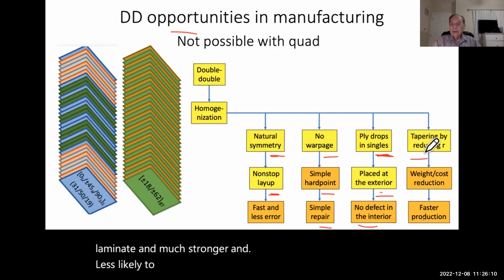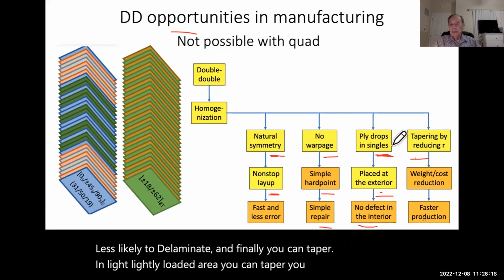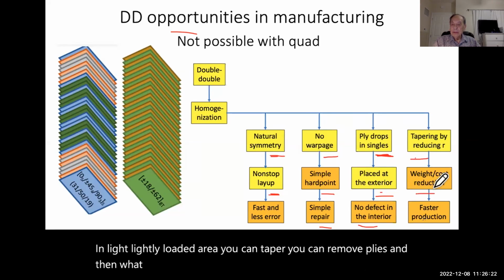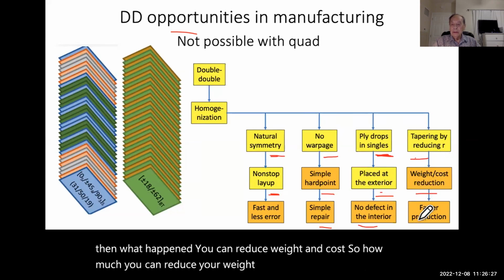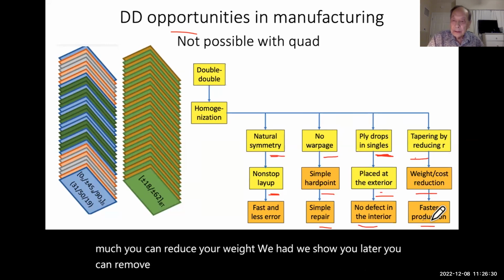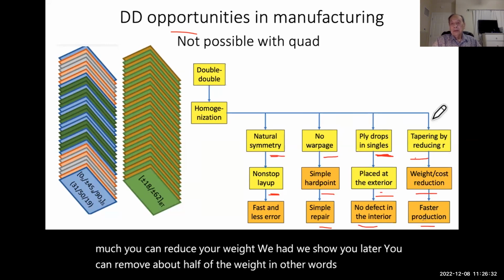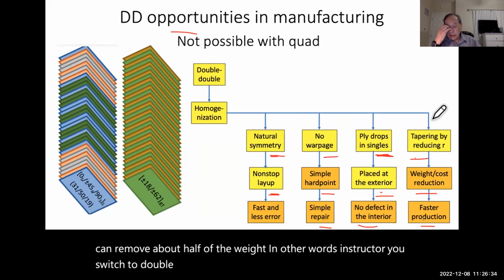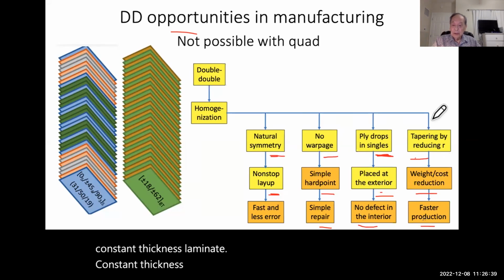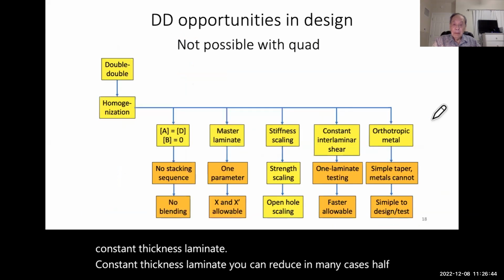And finally, you can taper. In lightly loaded areas, you can taper. You can remove plies, and then what happens, you can reduce weight and cost. So how much you can reduce in weight, we will show you later. You can remove about half of the weight. In other words, the structure you switch to double-double, as compared with a constant thickness laminate. Constant thickness laminate, you can reduce, in many cases, half or even more.